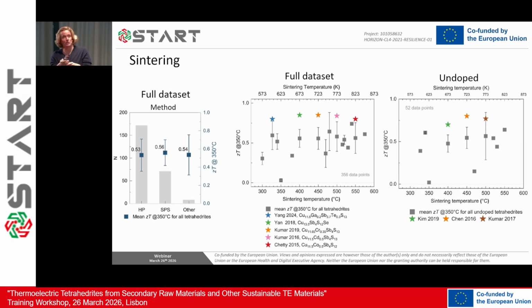I mean, you go from 300 or 350 to 550, and you get the same type of properties. It's very strange. Then again, is it a problem of chemistry? Then we removed it, we did it only for single compositions, and we did more than undoped - it's just that undoped is the set with the most data points. So we only have 52 data points at 350. And again, you don't see a very important contribution of the sintering temperature.